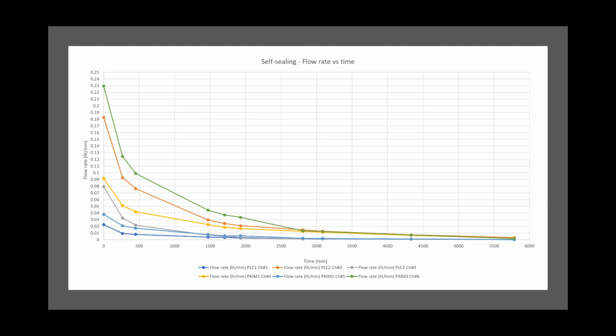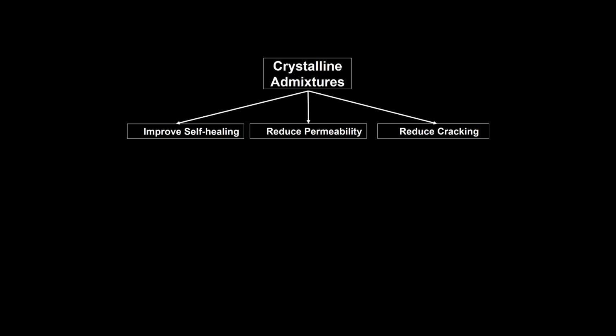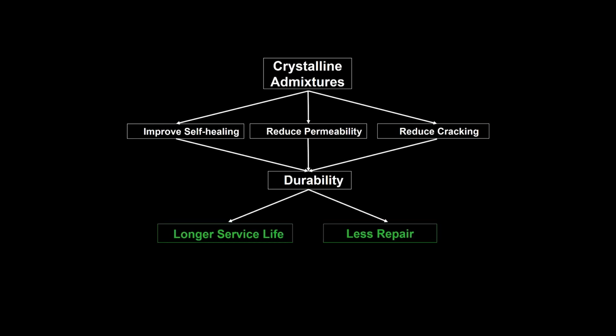To conclude, I used the crystalline admixtures to improve the self-healing phenomena inside the concrete, to reduce the permeability, and eventually to reduce the cracking size and cracking amount, which is critical for the repair process, because it's a costly process. In some way, I enhance and improve the durability of concrete structures, which leads to a longer service life and less repair cost. And what we believe in, we're going to make the concrete more sustainable.